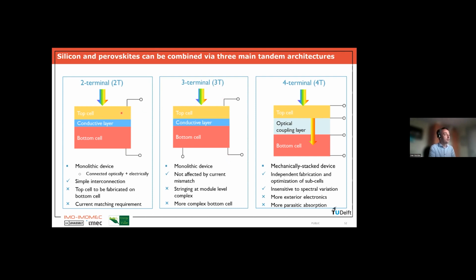So here you still have a monolithic device like the two-terminal. You grow the top cell on top of the bottom cell. But now you have not just a top contact and a bottom contact, you have a second bottom contact for the bottom cell. And this also allows, in case you don't have current matching, because the two devices are in principle series connected, that you don't lose part of the current. You can actually extract it via this third contact.